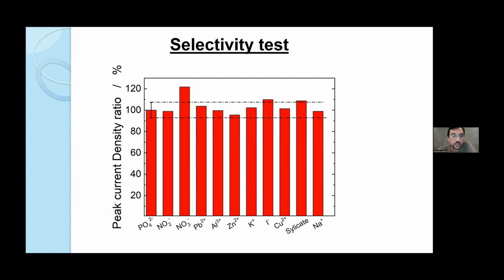But it's important to say that this experiment was carried out using a very high concentration of interfering agents, particularly 10 times higher compared to the phosphate concentration. So it is very unlikely to find a real water sample that has so high a concentration of nitrate ions.